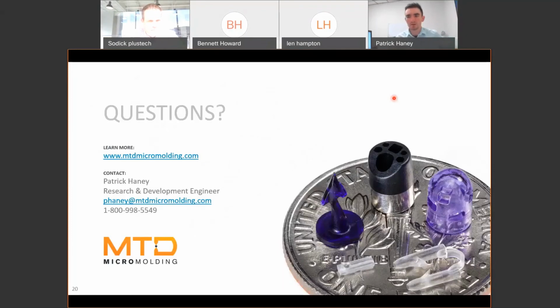Occasionally, yeah, we'll do that if we see it. We've done orifice diameter changes before. Sometimes they'll land inside the nozzle, because you gotta remember that the shear rate doesn't begin at the sprue bushing, right? It begins in the injection unit. So if you're running into some kind of shear rate issues and you can't address the mold for one reason or another, whether it's time sensitive or restricted due to the runner geometry or something like that, things like changing the nozzle orifice or how they interface with the sprue bushing, or even the land in the sprue bushing or the land in the nozzle, can all help to make quantifiable changes in your shear rate. Yeah, that will be noticeable.